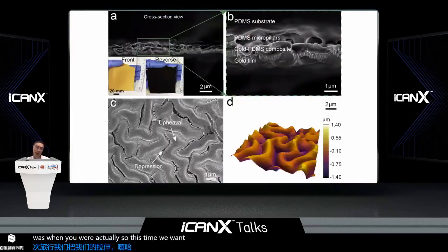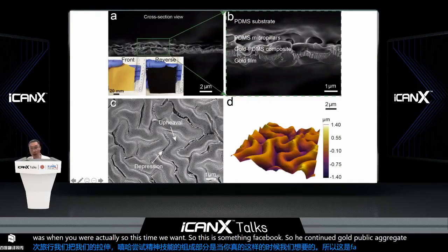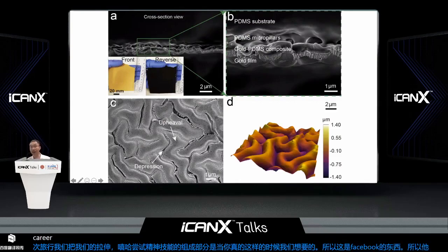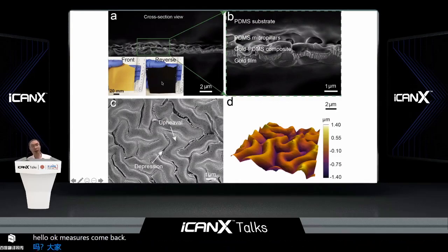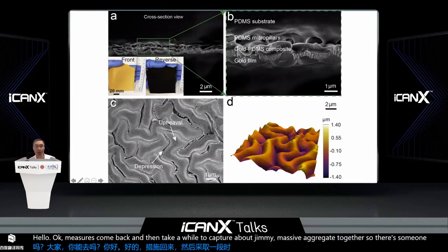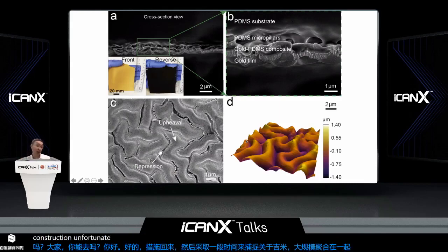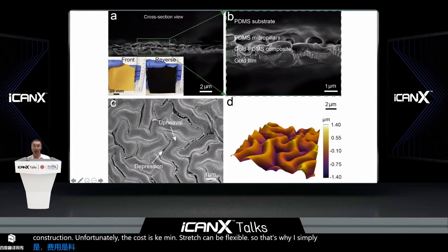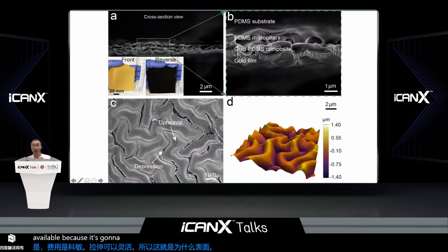Now look at the surface, how it looks. The front surface is gold in color, meaning the gold particles aggregate continuously. You can see here this gold film, continuous gold color. Okay, it makes sure it's conductive. And then the back one is black in color. Why? Because the gold particles are encapsulated by PDMS and form a composite aggregate together. So there is this kind of structure there. And because it can be stretched and is flexible, the surface is not uniform anymore. It's really like skin, with a lot of wrinkles there. Because of the wrinkles, the material can be stretched.